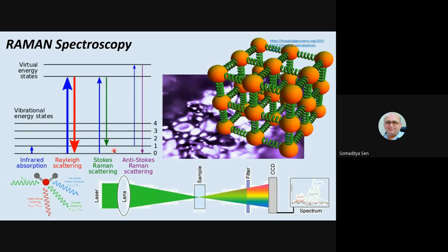If the strength of the bond between the two atoms is changed, we have a different force constant, and the force constant will give you a different frequency. So both the strength of the bond and the mass of the material involved will give you different types of vibrational spectra. So when you dope something, these things get altered, and you can check these differences by doing a vibrational Raman spectroscopy.